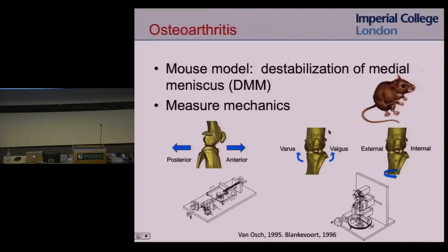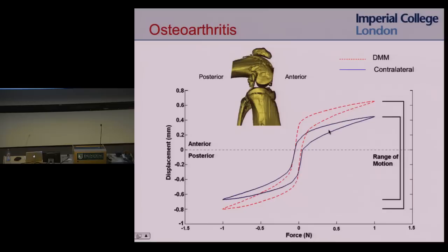So it's called a destabilization model, but nobody had ever measured the mechanics. So what are we actually doing? Are we actually destabilizing the knee? So we use these micromechanical testers that were developed in the Netherlands to measure knee mechanics. And what we do is measure anterior-posterior motion, pull it back and forth, varus valgus, which is side to side, and internal-external rotation. So here's an example of the laxity curve. So we bend the knee to about 60 degrees of flexion, which is typical for a mouse. That's their normal flexion angle.